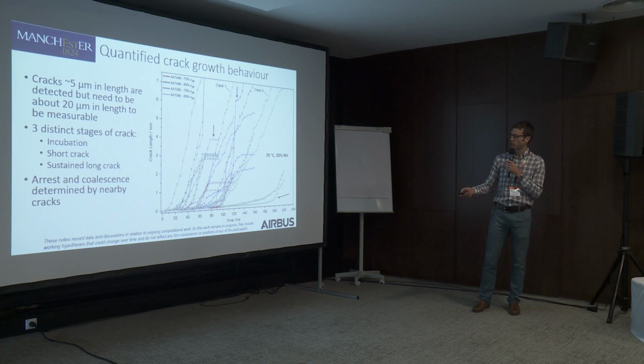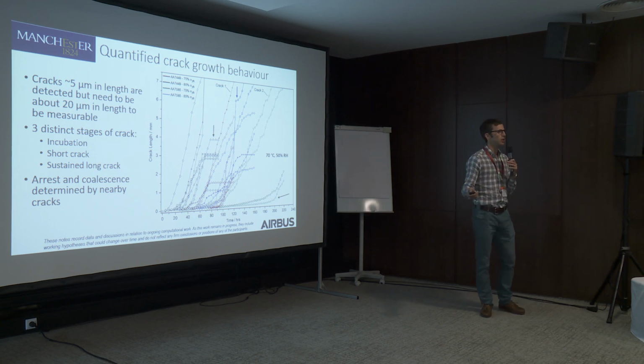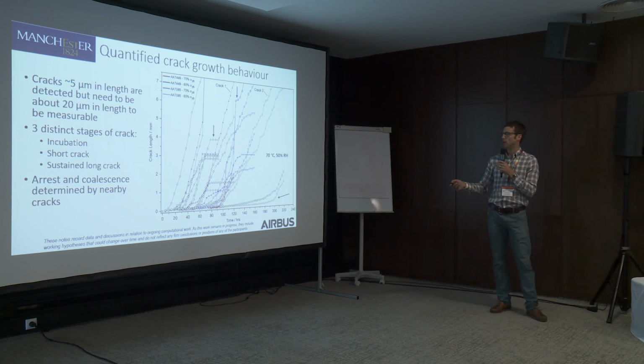And then we've got a short period of slower growth before it eventually reaches the sustained long crack behaviour. So all of these tests, again, were done at 70 degrees and 50% humidity. But there's also a lot of other things going on as we watch these cracks grow.